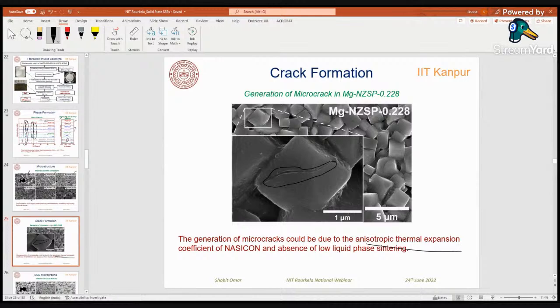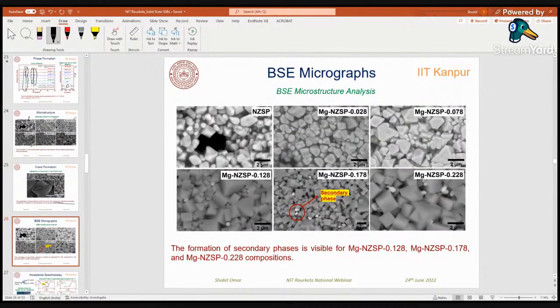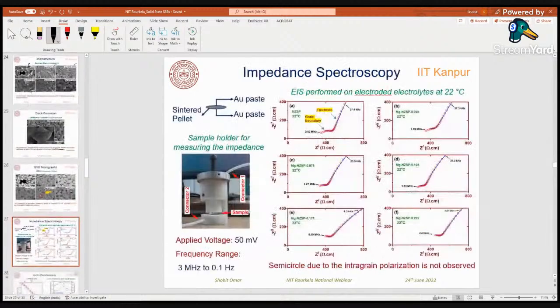When we look over the BSE images, we found some secondary phases present in the microstructure, and these phases are because of sodium phosphate or zirconia. But we are not able to distinguish between these two because they have similar binding energy, so EDS cannot differentiate between these two types of secondary phases, which are present in the higher composition material.